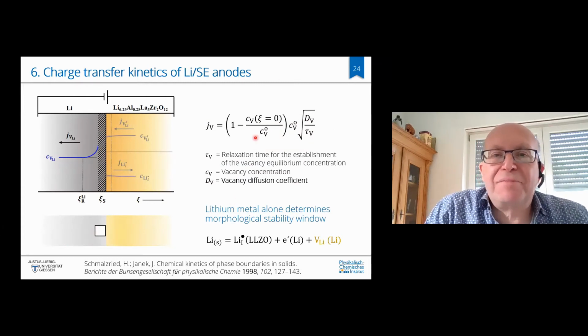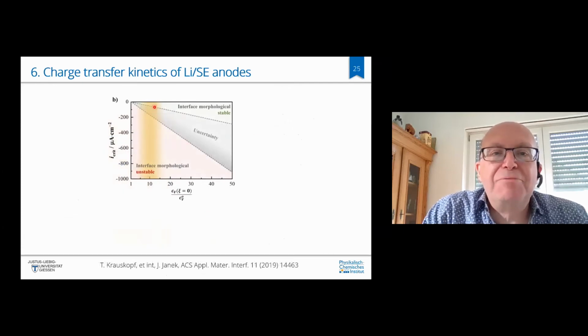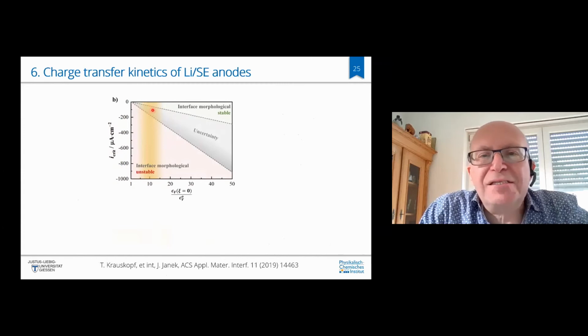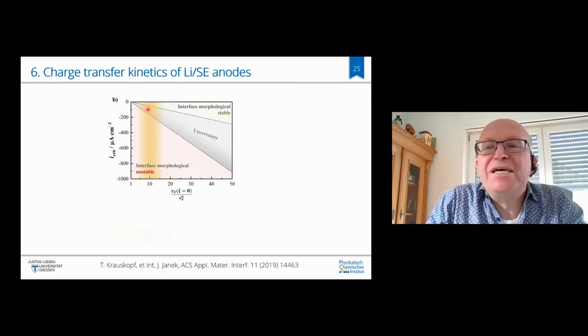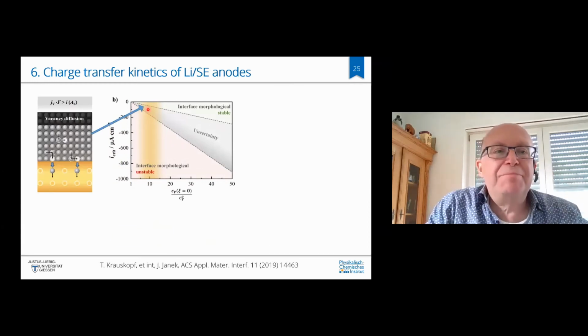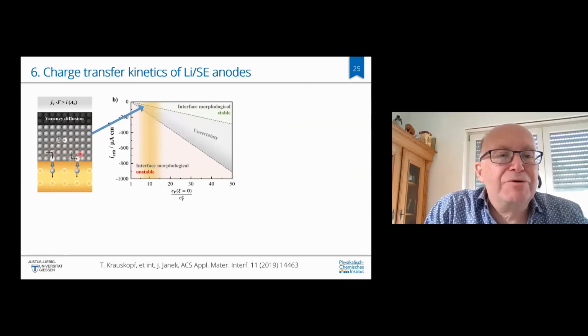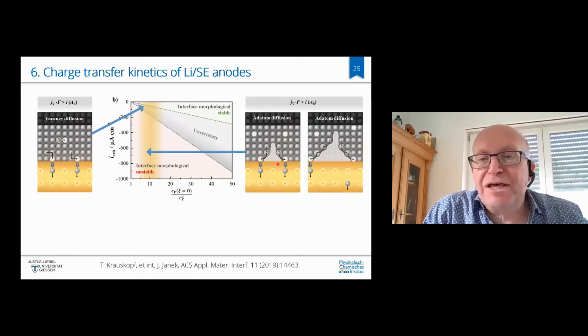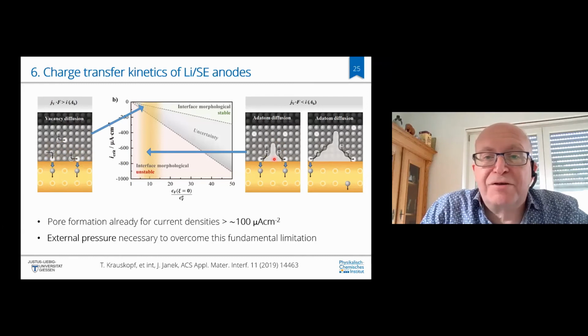But you can estimate this diffusion limiting current density. And we did that with quite a number of model assumptions. And then we came to the point that the critical current density below which you can stably cycle a lithium metal anode on a solid electrolyte, in this case LLZO, but I think this is quite representative, is about 0.1 milliamp per square centimeter. So all current densities above 0.1 milliamp per square centimeter at room temperature should lead to inherent unavoidable instabilities of the electrode. Simply by vacancy injection, the vacancies are not removed fast enough from the interface, and then they aggregate and form pores. And what we see is, of course, pore formation and the increase of interface resistance by the loss of contact. So this is, let's say, one important finding.